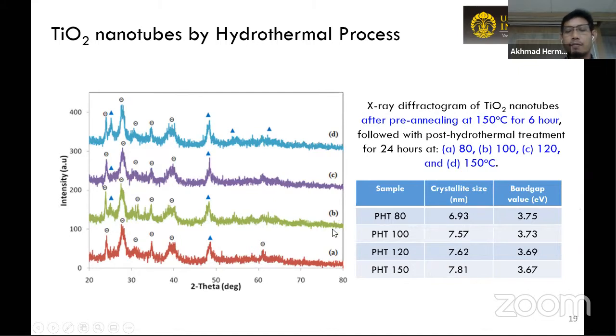And also we can see the band gap energy. So now we are concerned about the band gap energy. The band gap energy of the sample at 80 degrees Celsius post-hydrothermal treatment is still 3.75. The band gap energy was obtained using UV spectroscopy, and we used the Tauc equation to estimate it. By increasing the crystallite size of the anatase phase in the nanotubes from 7 nanometers to about 8 nanometers, the band gap energy decreased from 3.75 to 3.67. So it is quite promising that by increasing the crystallinity or crystalline size, we can adjust the band gap energy. Next slide, please.